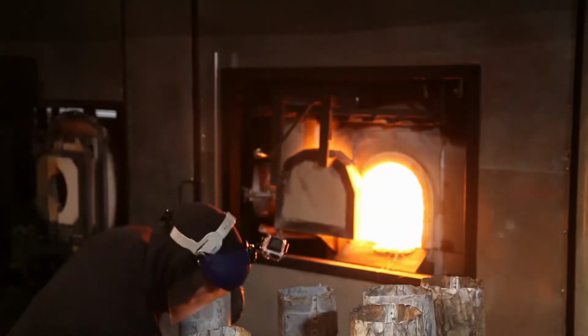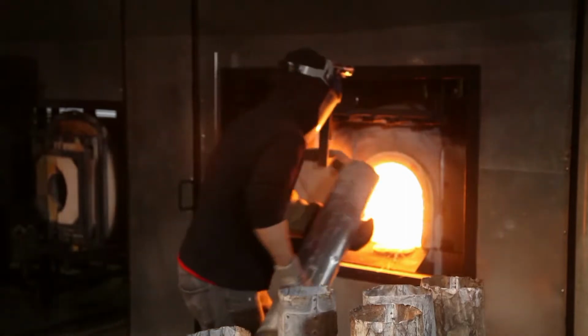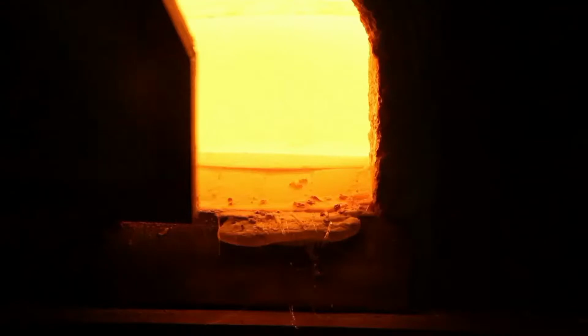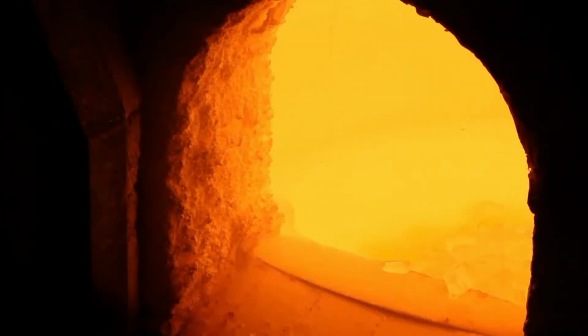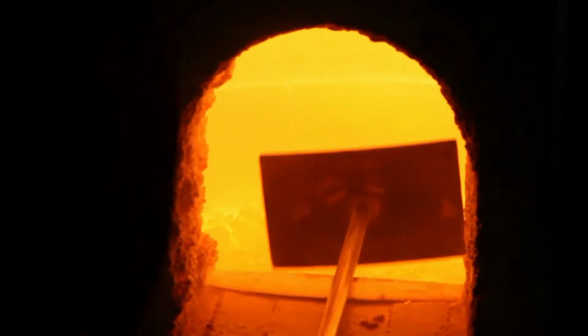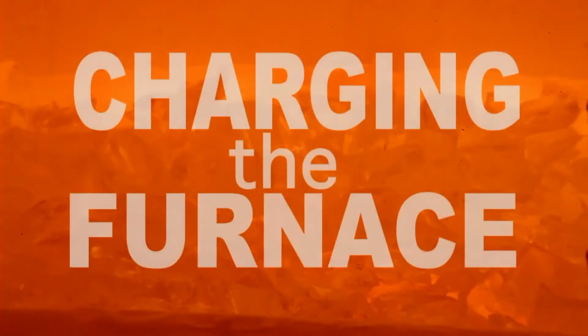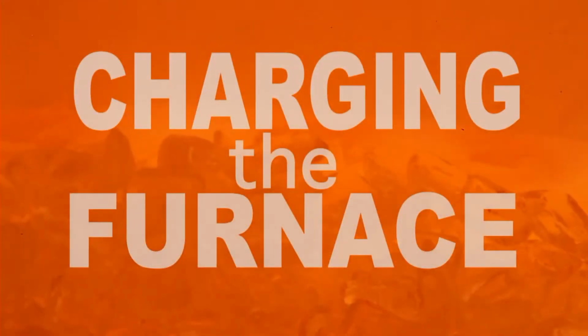The primary ingredient in glass is silica sand or silicon dioxide. The other two main ingredients are soda or sodium oxide, which lowers the melting temperature, and lime or calcium oxide to stabilize it. Once the cullet is loaded into the 2300 degree furnace, a rake is used to level the glass for even melting. The furnaces at the Museum of Glass hold approximately 1,000 pounds of clear molten glass and run continuously 24 hours a day, 7 days a week.